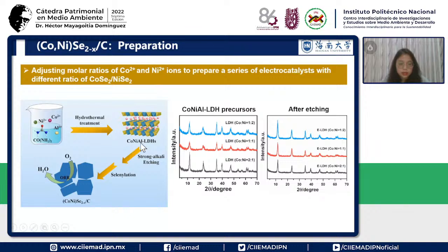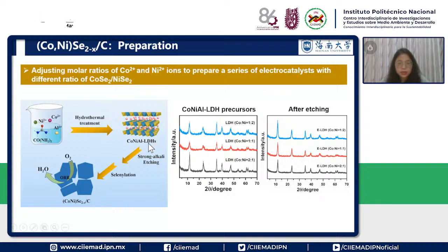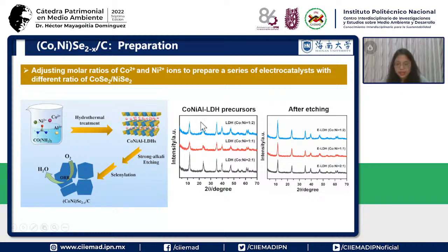At first, we got the cobalt nickel LDHs, and then we etch in the alkali. From the XRD we can see we got this material with the different molar ratios of the cobalt nickel LDH. After that, we are etching in the alkali to remove the inactive Al element. And then we just left the cobalt and nickel LDHs, because this tool is active for the ORR.